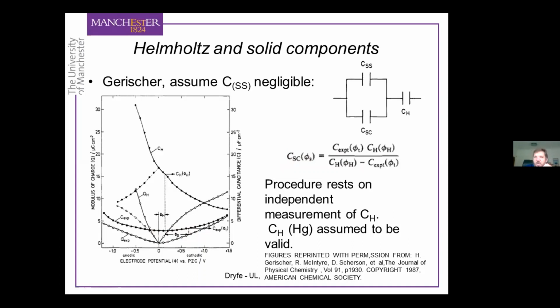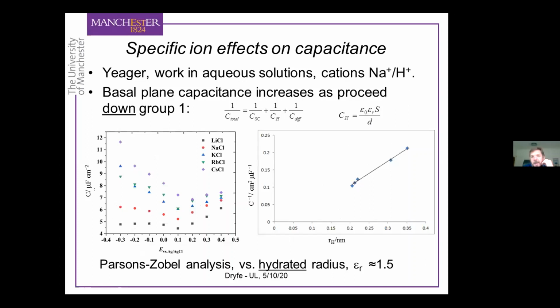He showed that the data he got agrees reasonably well with theory on the capacitance of the graphite. But as I say, it seems to me to rest on a rather questionable assumption, which is that the Helmholtz capacitance of the mercury, I think the solvent was acetonitrile, interface is the same as the Helmholtz capacitance of the graphite, acetonitrile, or whatever the solvent was, interface. And that seems like a slightly strange assumption to me. Because if those Helmholtz capacitances were the same, then you wouldn't think they would be sensitive to different ions, because Helmholtz capacitance is all about the adsorption of ions, and the adsorption of ions on mercury you would expect to be different from the adsorption of ions on graphite.